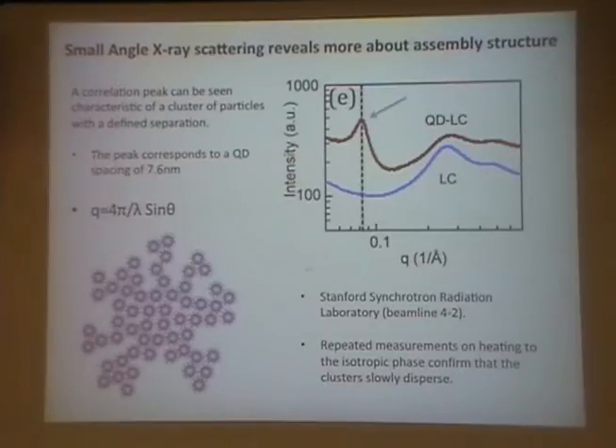I don't know very well about this, but usually in the case of micrometer-sized colloidal particles, when they aggregate, even in the isotropic phase, usually they will not disperse. This particle is very much smaller though. So what's the difference? Well, thermal effects would be a lot larger for such a small particle, because it's only a few nanometers in size. I'm assuming for the large colloid there's basically not much Brownian motion, but at the tiny size, they move a lot due to thermal effects.